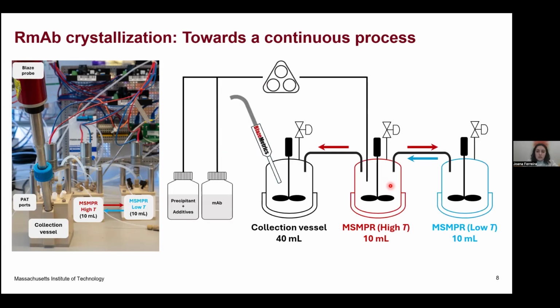So at this point, we also started thinking about how we can translate our concept of temperature cycling, a concept that has been applied for many proteins. So we are not reinventing the wheel. We are just making use of a very old concept in our favor. If we think about translating this to a continuous process, what we did was combine a series of MSMPRs, and basically we are transferring the material between the cold and the hot reactor. So it's the same concept. We try to dissolve the least stable form, the precipitate, in the hot reactor, and then in the cold reactor we are inducing the formation of crystals.